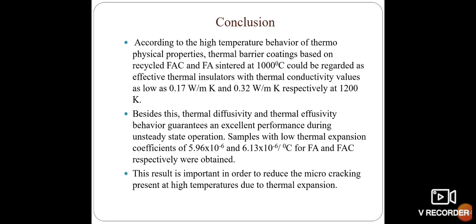The samples with low thermal expansion coefficients of 5.96 × 10^-6 and 6.13 × 10^-6 per degree centigrade for FA and FAC respectively were obtained. This result is important in order to reduce the microcracking present at high temperatures due to the thermal expansion. In general, we can conclude from the high temperature measurements and apparent high thermal stability presented in recycled fly ash cenosphere and fly ash thermal barrier coatings that it confirms their potential as thermal insulators for high temperature